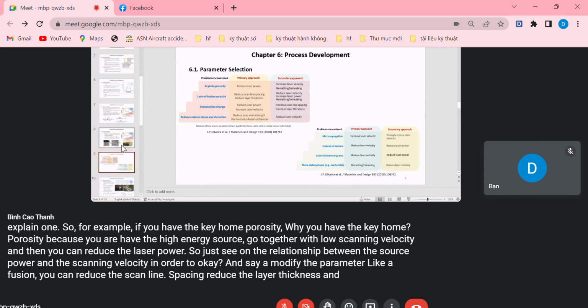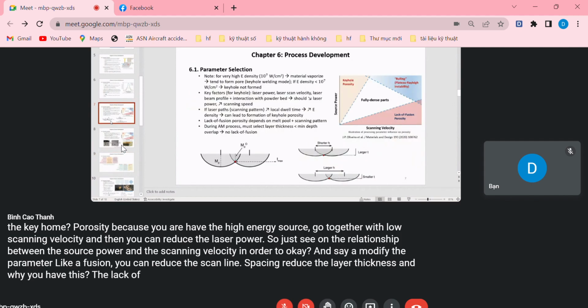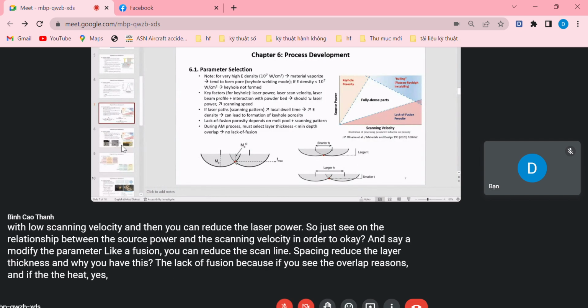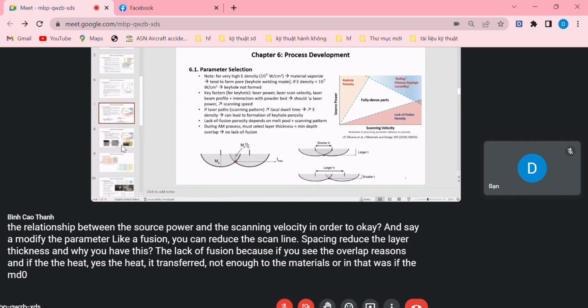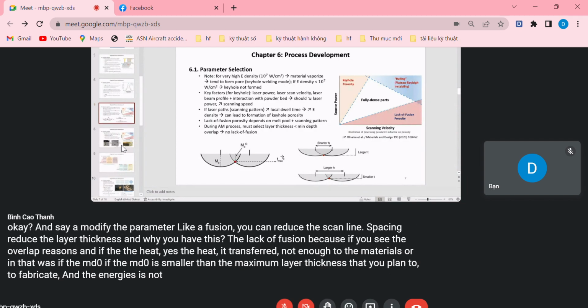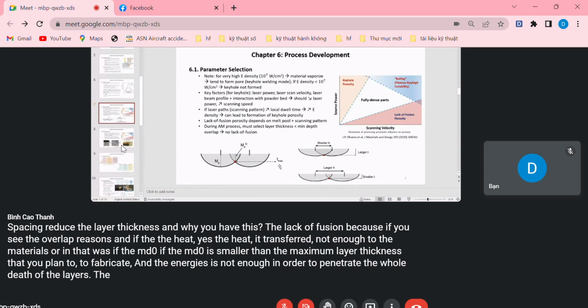And why do you have this lack of fusion? Because if you see the overlap regions, the heat is not transferred enough to the materials. In other words, if the melt depth is smaller than the maximum layer thickness that you plan to fabricate, the energy is not enough to penetrate the whole depth of the layer of materials.